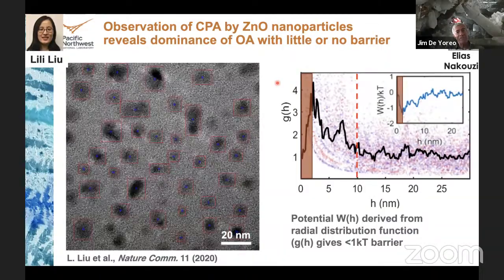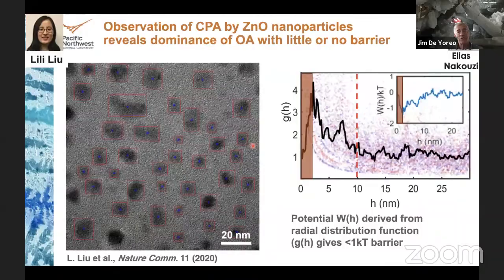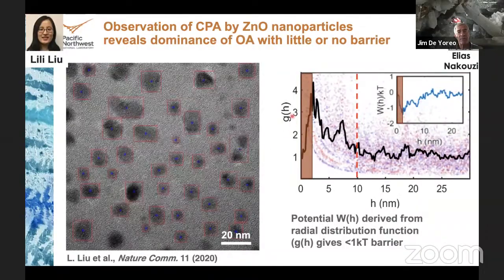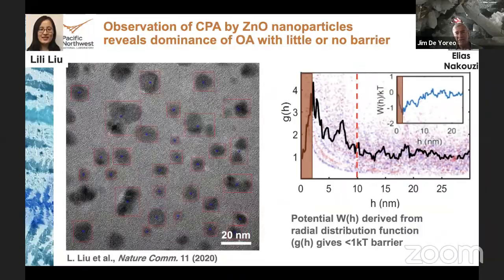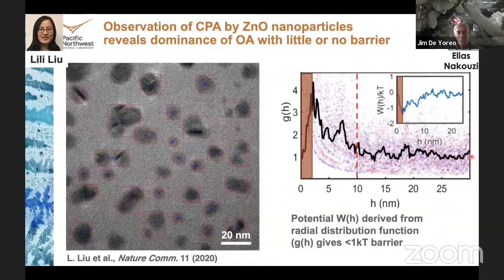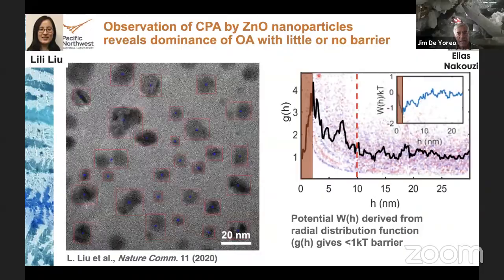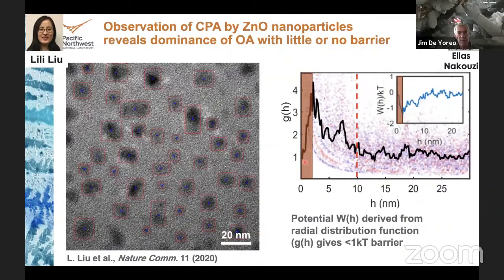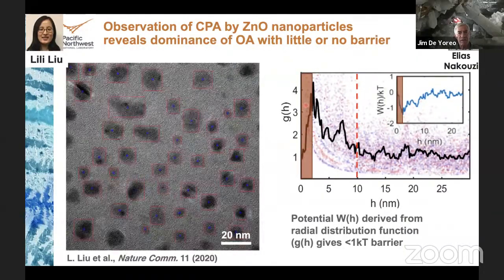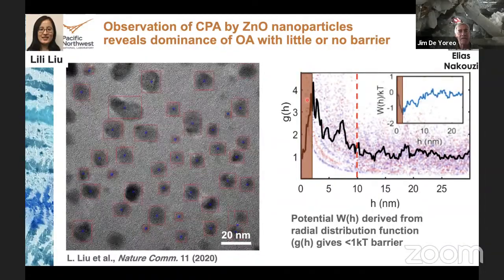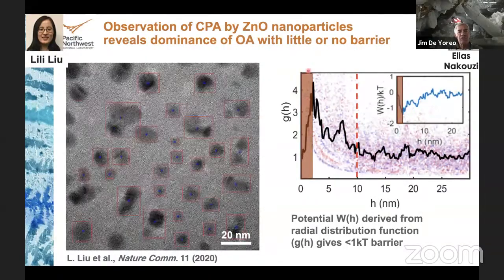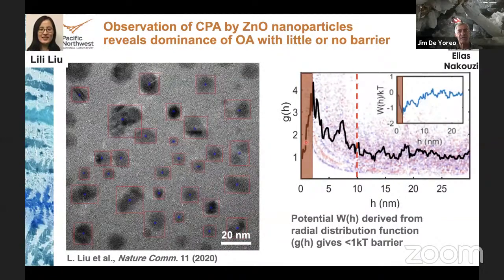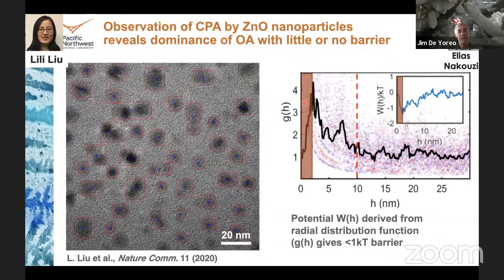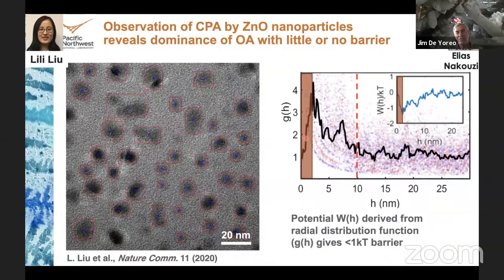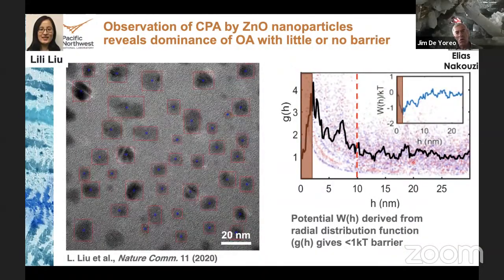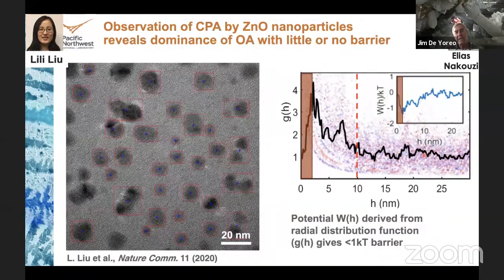If you analyze the position of every particle, you can create a radial distribution function, G of H, where H is a separation. And the radial distribution function looks like this. It's a smoothly increasing curve. I've blocked out this region because the problem is that once the particles get to within a couple of nanometers, they jump to contact very rapidly. And so this region is always devoid of particles. They never exist in this region. So the G of R is not valid here. But for all the data, the black curve is the average, and at all frames of the movie, they look like this.